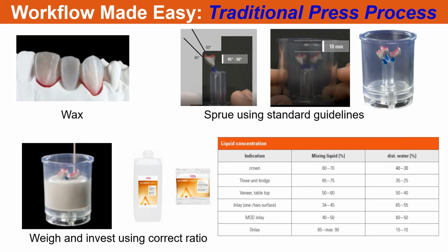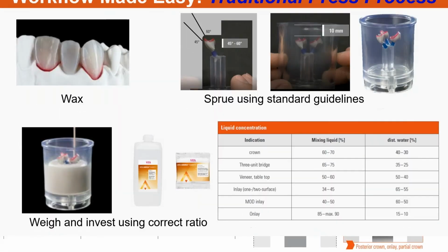You have to have the restoration when you sprue it, you know, think of it as a flower coming off the sprue. It has to flow out as even as possible without hitting right angles. So it's got to have a nice flow. If it doesn't, then you sometimes find yourself having to increase the press temperature, but that can start affecting the shades and also start affecting that reactive layer that naturally occurs with lithium disilicate. There's no way 100% completely around that reactive layer, that whitish material, but there is like investments. The Ambria investment itself actually helps you alleviate that material.